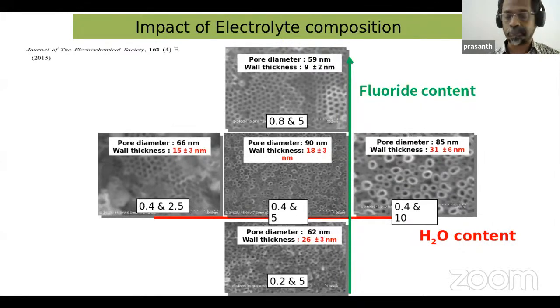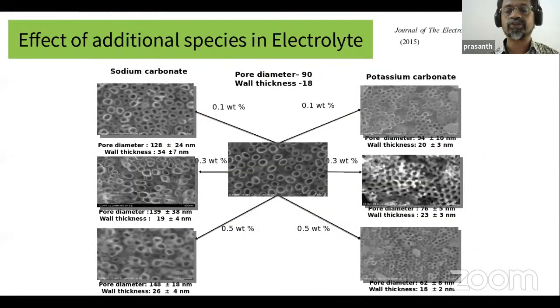So many things you can play with in the fabrication of nanotubes, and the extra species coming into the electrolyte is basically an etching and regrowth process. So you are using the fluorine to etch the titanium surface in a controlled way. You will get a porous structure, where the removed TiO2 is again redeposited over the nucleated regions, and it is regrown. That is a simple way of viewing the growth of the nanotube structures.